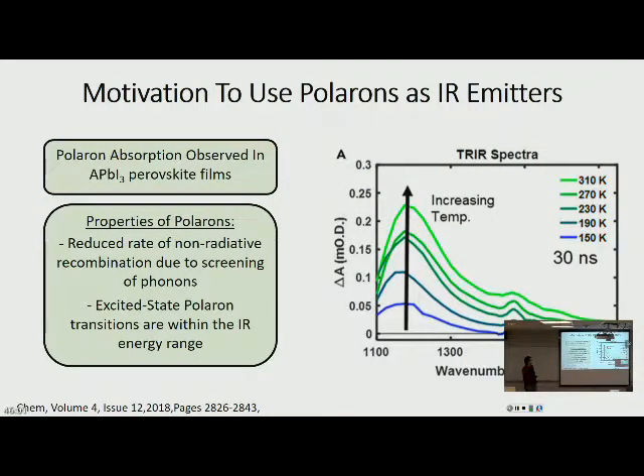So this just shows there is polaron formation in these perovskites. The axis they use is wave numbers, but I think this transition at 1200 wave numbers is about 8,000 nanometers, so 8 micrometers. What does TRIR mean? Time resolved IR spectra. I think it's a pump probe, so the pump is visible. Right, so they create the polaron. This perovskite structure will not absorb in the near IR if it is not excited beforehand with optical light. You have to form the polaron first, and then probe it.